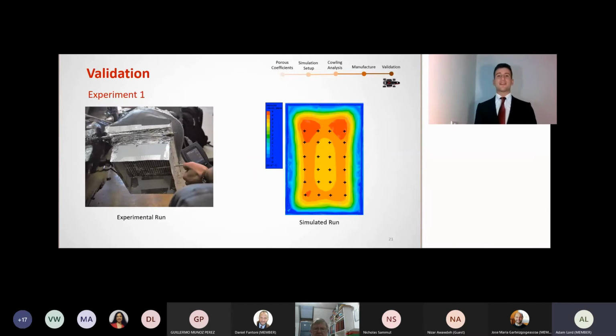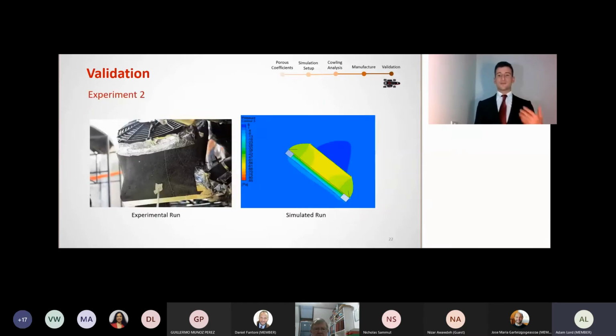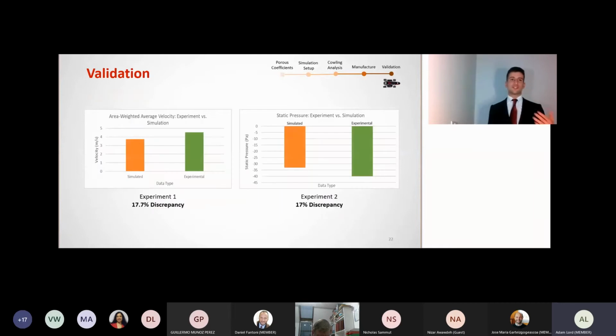An identical simulation was then set up in ANSYS and compared to experimental results. The second part involved a single static pressure tapping on a suitable location on the shroud, which allowed for a direct comparison to the pressure found at the same location in the simulation. A discrepancy of 17.7% was found in the first experiment, and similarly 17% was found in the second one.